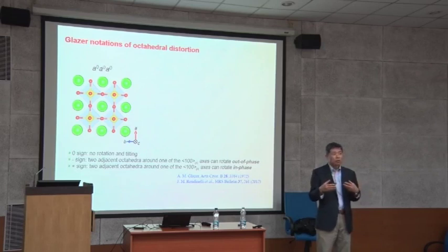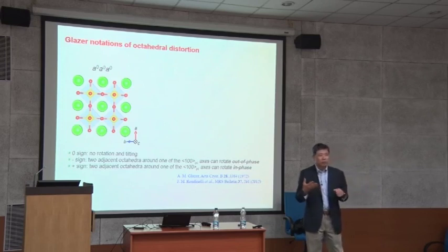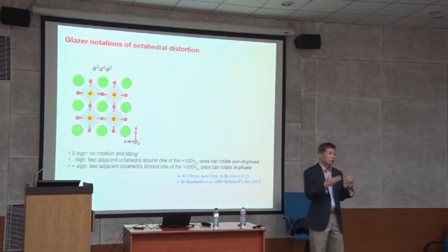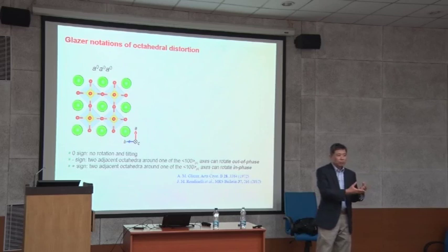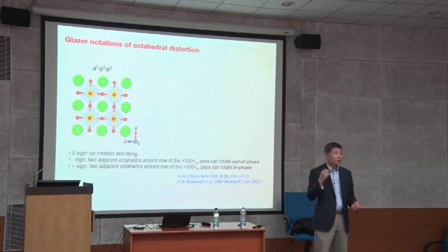So in order to reduce this, they cool down to around 600 degrees C and then do oxygen annealing for an hour, a very long period of time. So they vent oxygen close to atmospheric pressure and leave it there for an hour. The reason they use 600 degrees C is that you have competing factors in this annealing, and this is important, a lot of people should know. If you go to very high temperature, then the equilibrium vacancy concentration increases. You know this equation, right? Exponential of activation energy or formation energy over kT.